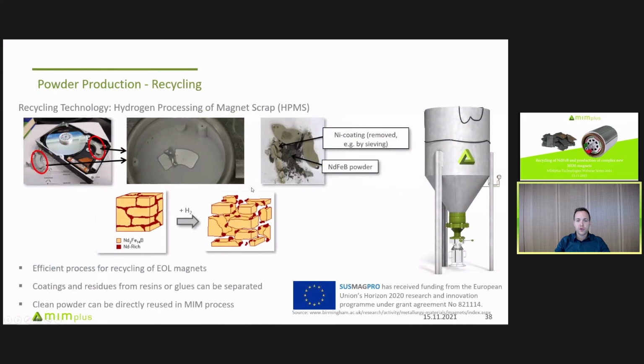The recycling route, as Carlo showed, is that you introduce a permanent magnet into a hydrogen atmosphere, then the whole magnetic microstructure falls apart, and you only have to guarantee to collect the powder and to separate it from the coatings or other residuals like organic carbons, glues, resins, and so on that could be on top of the magnets. And the clean powder can be directly used for the MIM process.